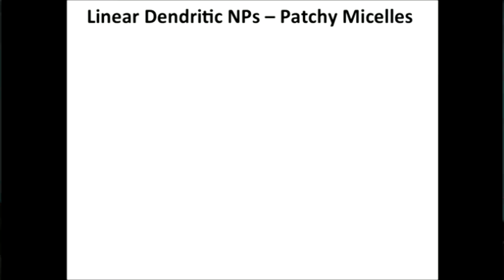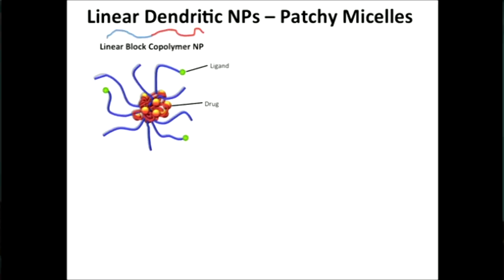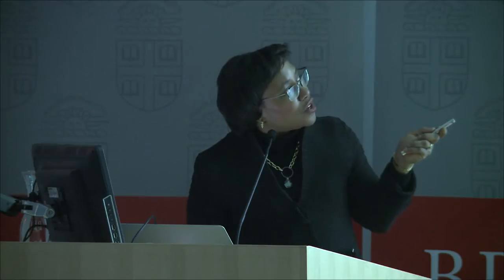And this led to the development of a new polymer system. Typically, what we would do is make a polymer system. These are large macromolecule systems in which we have two blocks, a length of molecular repeat, here shown in blue, which is very water soluble, and one shown here in red, which is not water soluble. When these assemble in water, the hydrophobic groups will cluster in the core and we'll be able to encapsulate drug into that core region. Then this water-soluble region is allowed to be presented, and for the one that we chose, which is polyethylene oxide, it can present this very hydrated stealth layer. All right, and then we can attach a ligand. So this is a standard sort of approach, linear block copolymer.